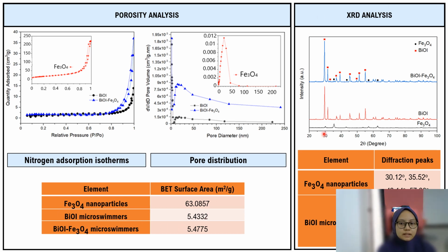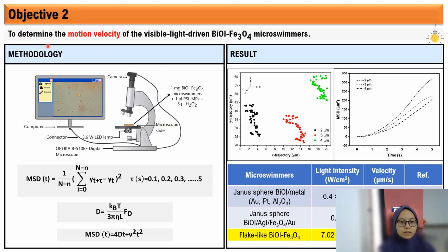From the XRD analysis, it can be observed that new diffraction peaks on the bismuth microswimmers indicate the presence of iron, and the BiOI-Fe3O4 has a crystalline structure. The second objective of this experiment is to determine the motion velocity of the BiOI-Fe3O4 microswimmers.